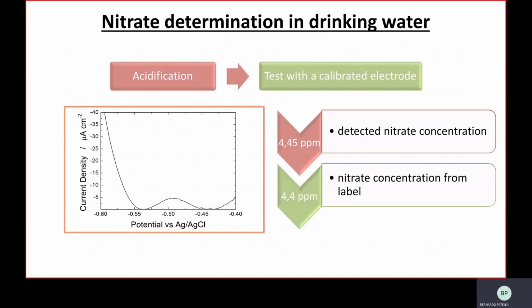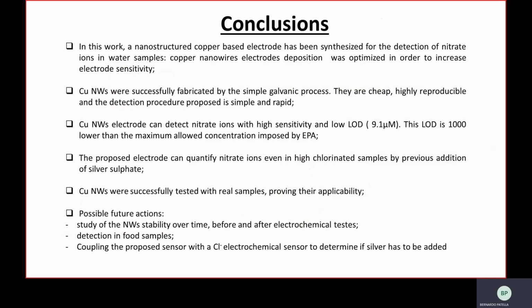the proposed sensor. So, concluding, in this work, a nanostructured copper-based electrode has been synthesized for the detection of nitrate ions in water samples. Copper nanowires electrode deposition was optimized in order to increase the electrode sensitivity, and the nanowires were successfully fabricated by the simple galvanic process. The electrode synthesis is cheap, highly reproducible, and the detection procedure is simple and rapid.